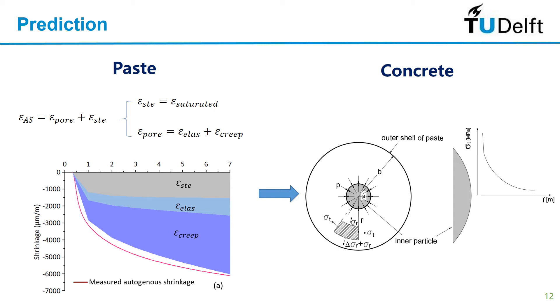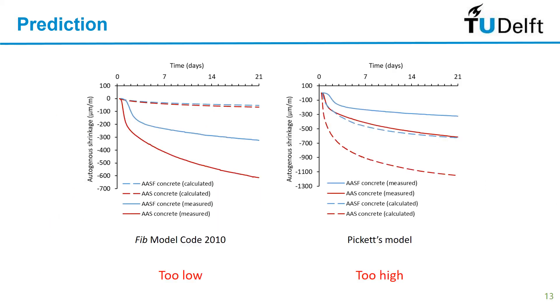We have a lot of models available for Portland cement concrete but not all of them work for geopolymers. For example, we found that the fib Model Code tends to give a very large underestimation of the autogenous shrinkage of alkali-activated concrete, because the relationship between strength and shrinkage for alkali-activated concrete is different from Portland cement — the empirical parameters identified for Portland cement are not applicable. We also have composite models like Pickett's model or Hobbes' model, and we found these tend to overestimate the shrinkage, because they treat all deformation as elastic. The restraining effect of aggregates on elastic deformation and on creep deformation are different; if we assume all deformation is elastic, we underestimate the restraining effect and overestimate the shrinkage.